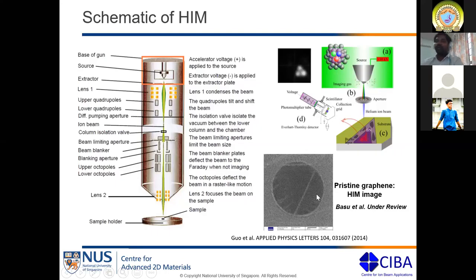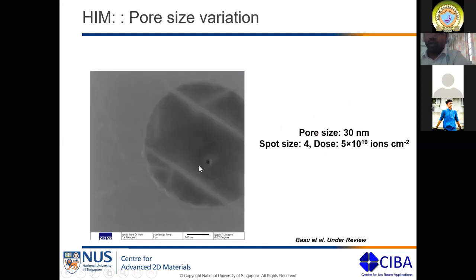When you transfer graphene, sometimes you don't have a fully flat graphene. There might be folds and wrinkles on the graphene due to transfer problems, and this is one of the examples. So here I show some openings that I can create using this kind of highly focused ion beam. This is an example where I can create a 30 nanometer hole in a freestanding graphene membrane. You can see this black dot, which is about 30 nanometer. And we have used this kind of helium ion microscope technology.